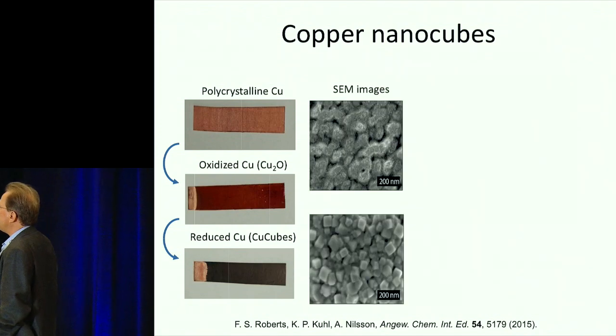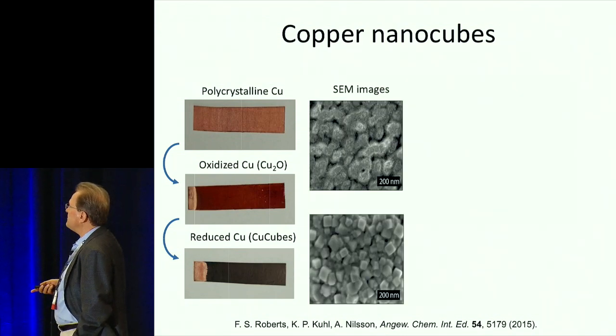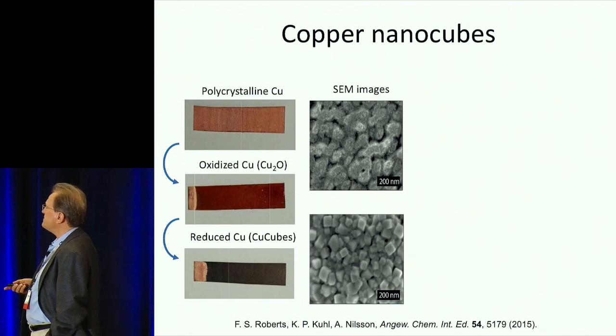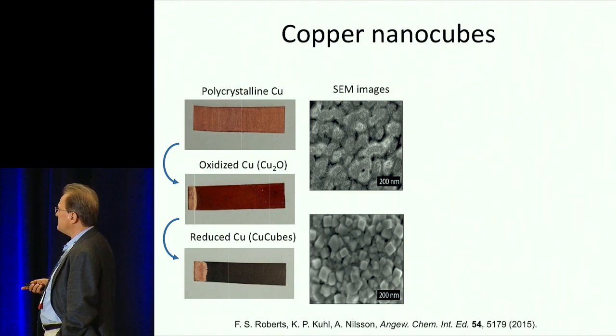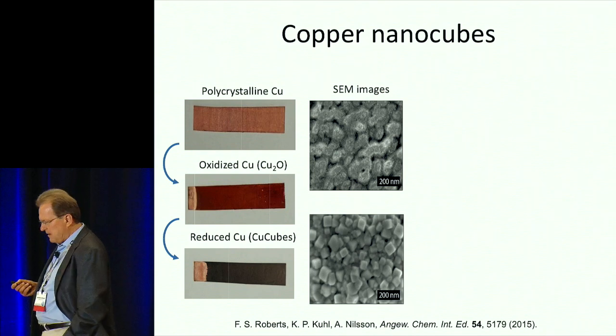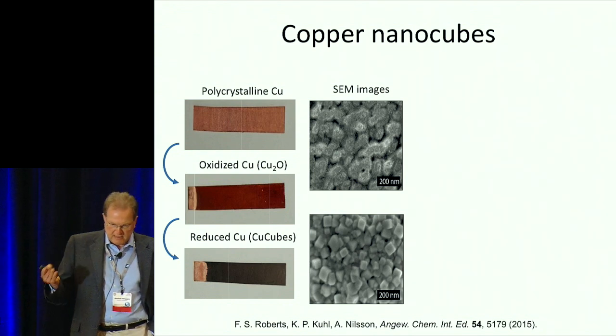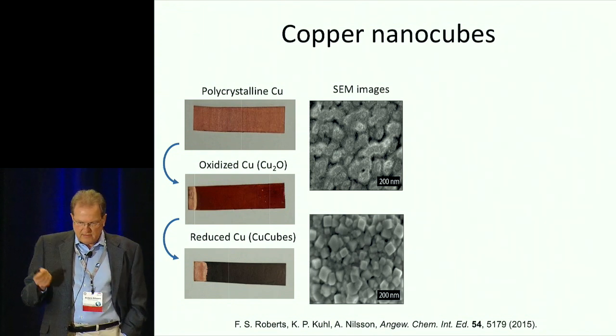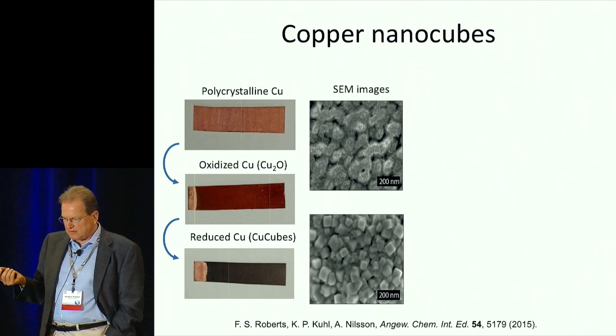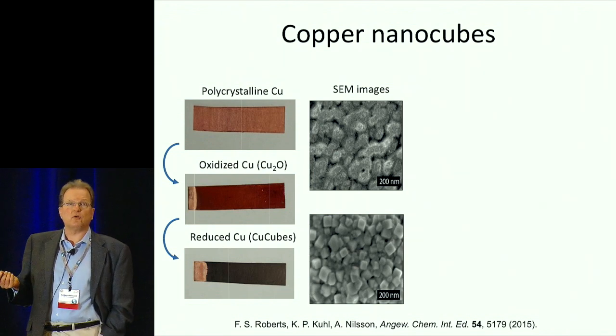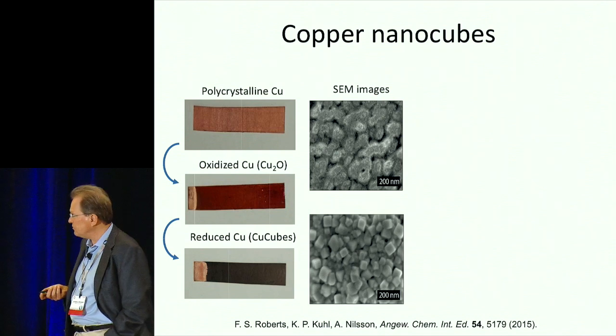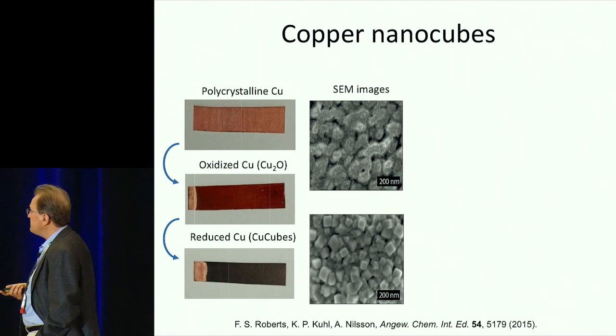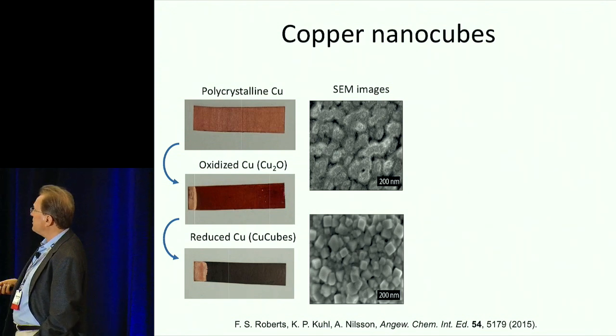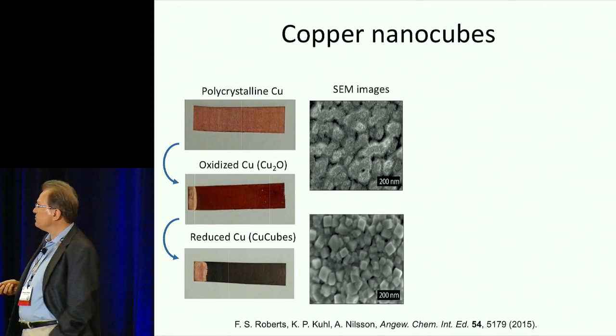What we have recently done is that we have actually discovered a very interesting copper nanocube catalyst if you run CO2 reduction in an electrochemical environment. This was discovered by accident. One of the postdocs had a leaking electrode, so they got chloride into the solution. They observed this cube structure of copper as you reduced it, so to speak.